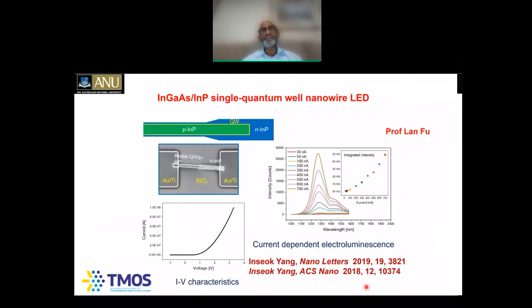So till now, I've only shown you optically pumped lasers. Now what we want to do is electrically pumped lasers, because that's what industry wants. This is the work of Dr. Inseok Yang, who is now at Samsung as a research engineer. In Suk has spent a lot of time optimizing the doping of this indium phosphide with a P-type dopant, zinc. Then he's grown an indium gallium arsenide quantum well, this yellow region here. And then the top contact is N-type indium phosphide, which is doped with silicon.